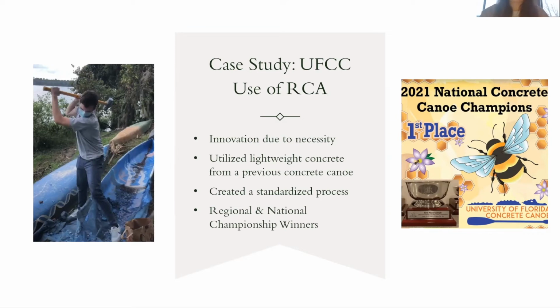Following the production and testing methods that Wes outlined in the previous slides, we started out by manually crushing the concrete at our lakeside storage facility in order to easily transport the concrete back to our lab and to be able to feed the material into our pulverizing machine. With this pulverizing machine, we were able to produce granular concrete sizes that could be sieved. The material that was retained on the number 8, the number 16, the number 30, the number 50, and the number 100 sieve were considered usable and was stored in airtight buckets in order to remain at a consistent moisture content.